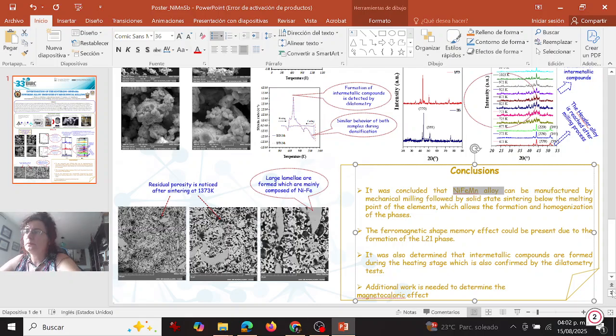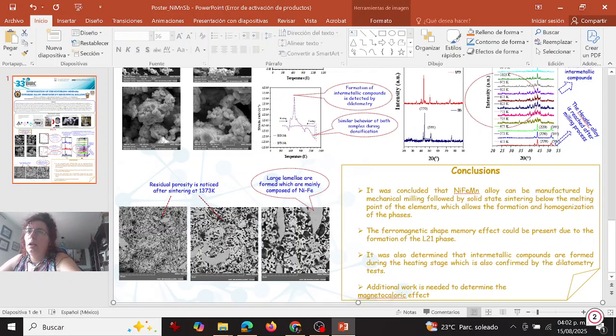So in conclusion, it was concluded that NiFeMn alloy can be manufactured by mechanical milling, followed by solid-state sintering, below the melting point of the elements, of course, which allows the formation and homogenization of the phases. Another conclusion was that the ferromagnetic shape memory effect could be present, and this is due to the formation of the L21 phase. It was also determined that intermetallic compounds are formed during the heating stage, which is also confirmed by the dilatometry tests. And the last conclusion was that additional work is needed to determine the magnetocaloric effect.